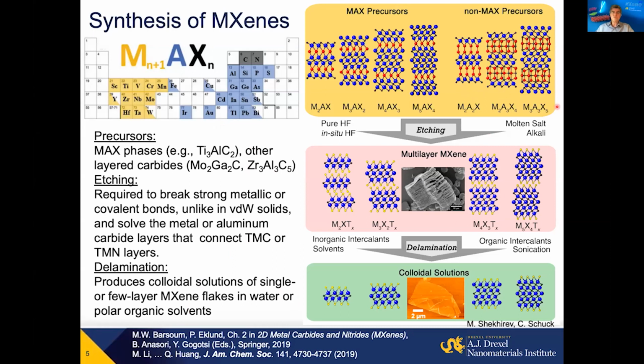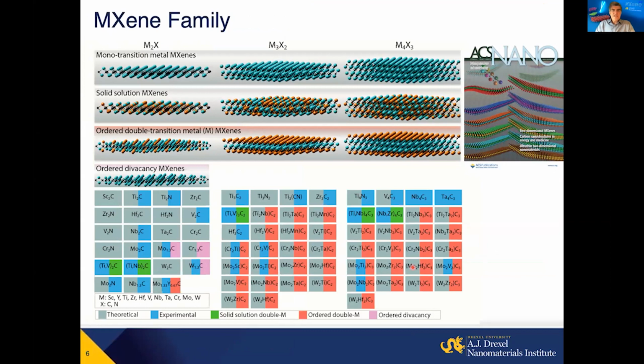There are other ways to make MXenes. For example, it's possible to start from layered carbides which are not MAX phases, for example, aluminum carbide layers connecting zirconium or hafnium carbide layers here. It's possible to use molten salt, alkaline solution, or electrochemical etching to produce these MXenes. But what is important at the end of the day, we end up with single layer flakes of carbides, nitrides, carbonitrides of transition metals with a variety of properties here. Moreover, we can really exercise engineering of materials at the atomistic level with this approach.